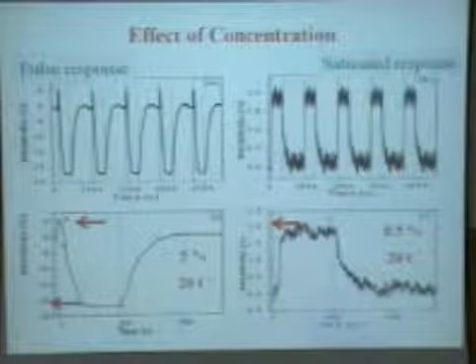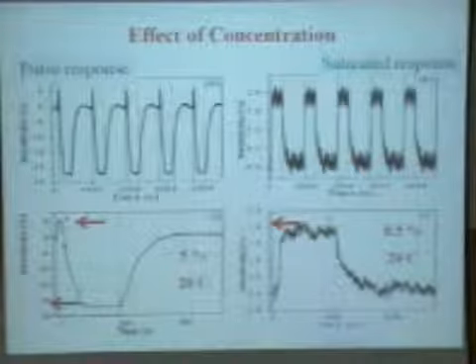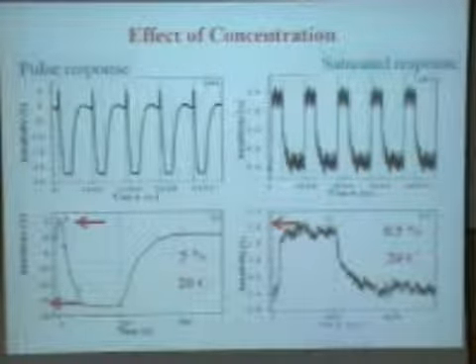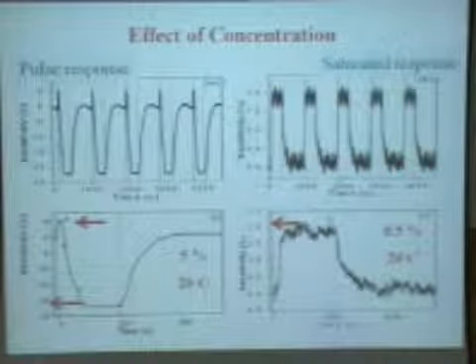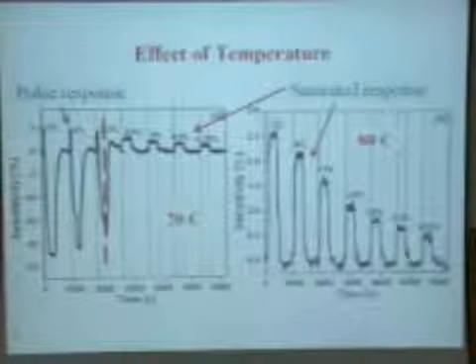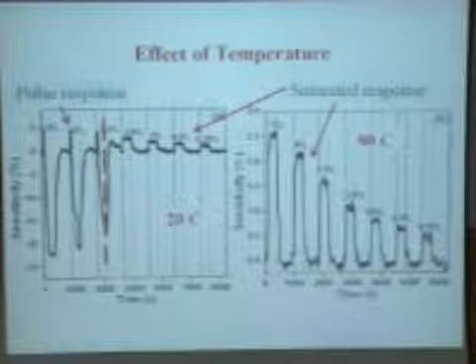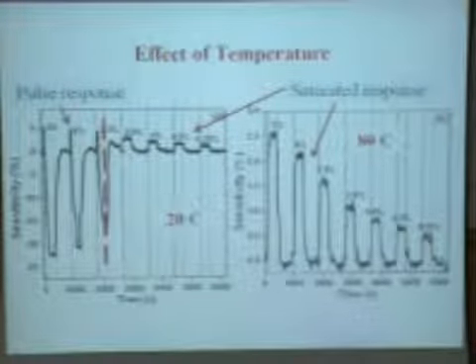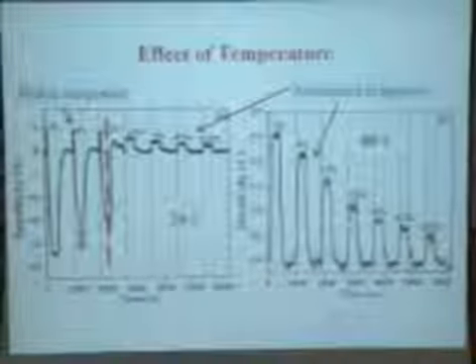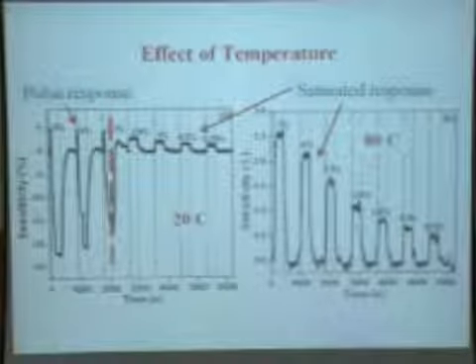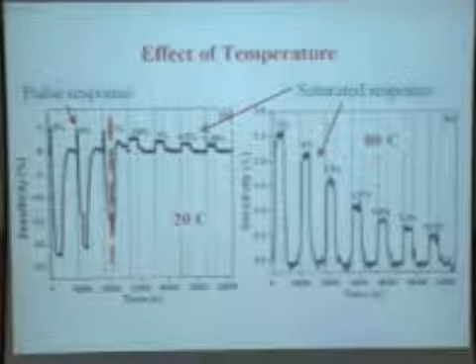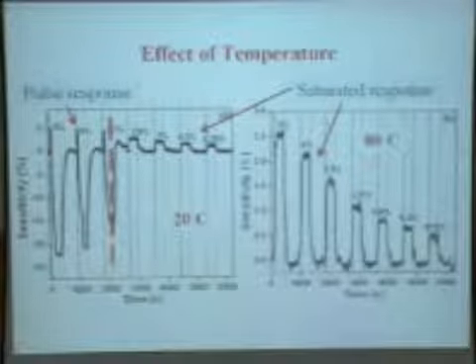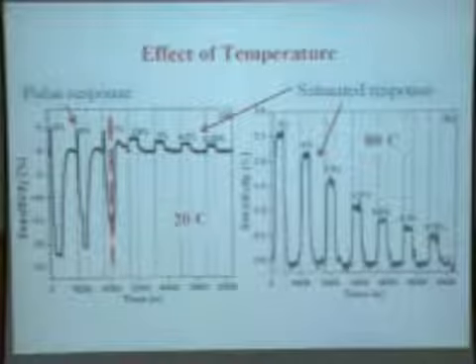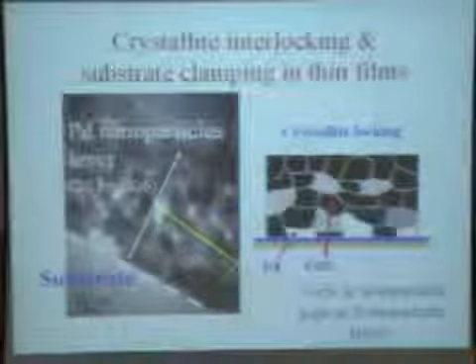Okay, and we did a lot of measurements, and as you can see here, at 5% hydrogen, at 20 degrees centigrade, you have a pulse-like response. At 0.5% hydrogen, you have a saturated response. Same thing happens with temperature. If the temperature is 80 degrees centigrade, at all hydrogen concentrations, you have a simple saturated response. If the temperature is 20 degrees centigrade, below 2.5%, it is a slow saturation response. Above 2.5%, it is a pulse response. Okay, so I think I will skip this.